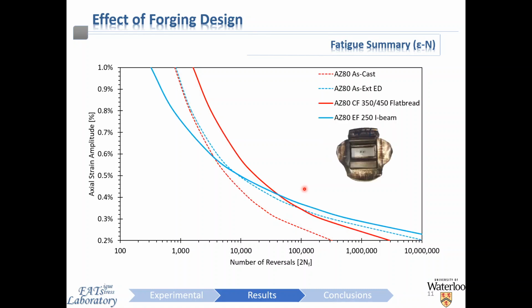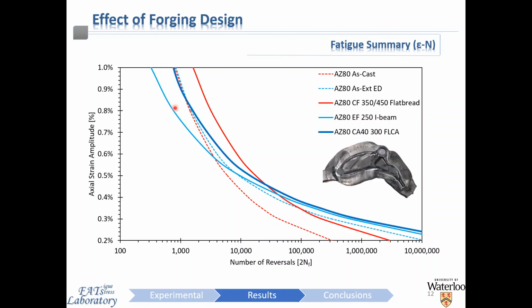However, when we look at the extruded and forged material, which was forged in a totally different configuration of forging now, which was this closed die I-beam type shape, the differences are not quite as simple. Since the starting material was wrought to begin with, there is a more modest modification of the properties due to forging. In general, an improvement is always observed in the high cycle regime, as seen here. However, at lower forging temperatures, limited ductility in the material might cause a small degradation in the strain control fatigue behavior, as we can see here.